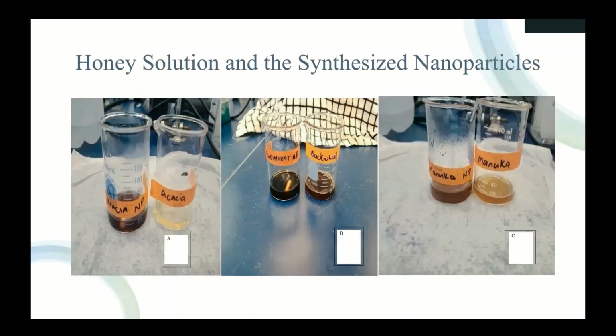So this is how we know that we synthesized the silver nanoparticles. As you know, a chemical reaction is always indicated by a color change. When we did the stirring and the heating for 30 minutes at 60 degrees, there was a color change for the nanoparticle formation, and we see the three different honeys and the three different colors for the acacia honey, the manuka honey, and the buckwheat honey. You can see that there's a color change. We do not have a way currently of actually characterizing the formation of the nanoparticles, such as using SEM or UV-vis. Next slide.